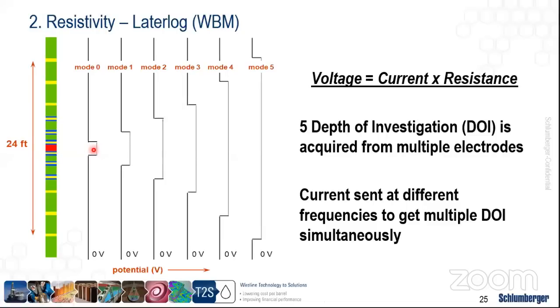The deeper the current goes into the formation, the more depth of investigation that we have. And the shorter the current goes into the formation, the less depth of investigation we have. Typically, a Laterolog has 5 outputs. So it has RLA1, or let's say the shallowest resistivity, which is the one that's very close to the borehole, all the way up to RLA5, which is the Laterolog at the depth level of 5. And this is the deepest resistivity that can be measured, and this should be representing the RT, which is the true formation resistivity of the reservoir.